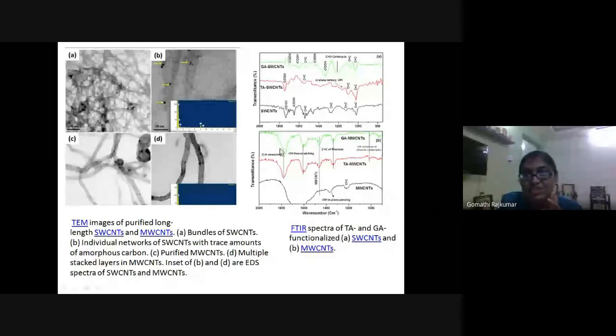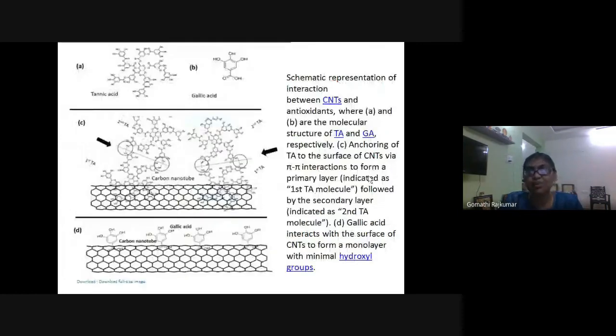Now, this shows CH stretching, OH stretching, C double bond C stretching, and OH vibration of phenolic compounds. So, this FTIR clearly shows you that multi-walled carbon nanotubes existed with the tannic acid. Similarly, single-walled carbon nanotubes also existed with tannic acid, which means the functionalization, the mixing, was completely positive. Okay, so if you could ask me what actually was the bonding mechanism, this is actually the bonding mechanism.